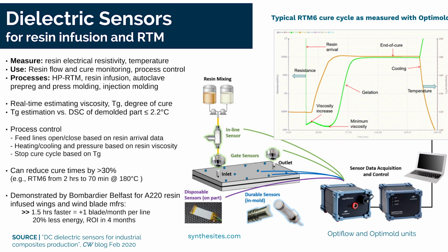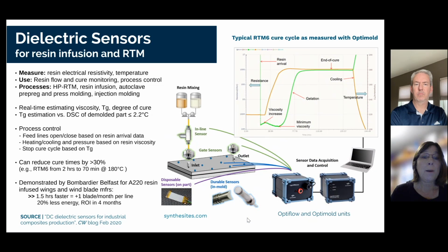To give you an idea of what these look like, that's the in-mold sensor right there, and it will be in contact with the resin as it's going through the injection or infusion. That's a disposable sensor that can go on the part. And then you have to have a wired connection from these sensors into the data acquisition, and then it feeds into the analysis tools, right? So when we look at this data and we're measuring this data, what it allows these companies to do is then take that and do real-time estimating of viscosity, Tg, and degree of cure.